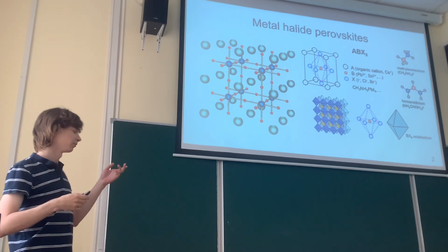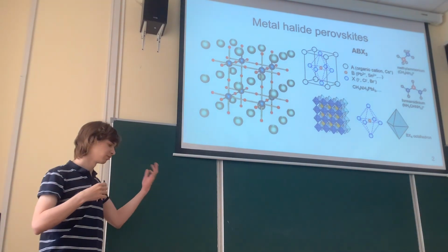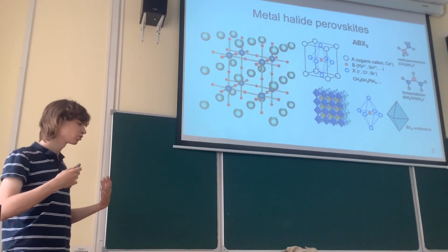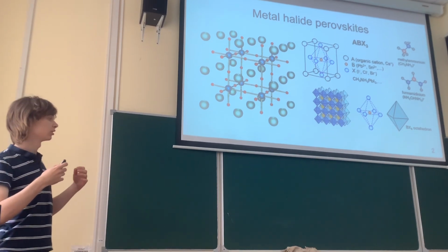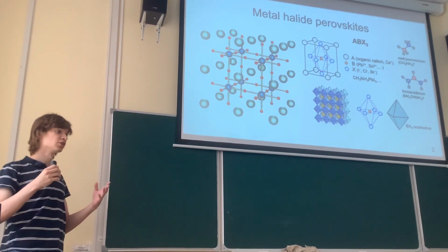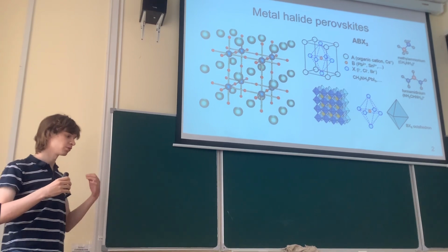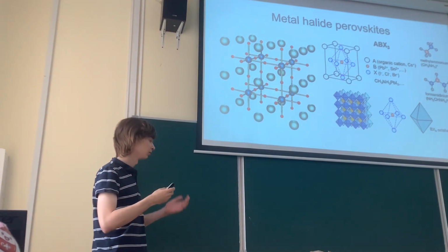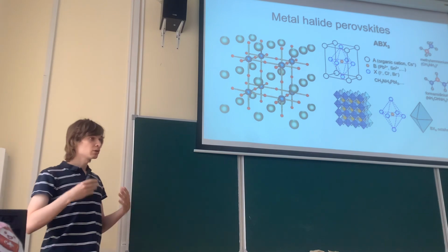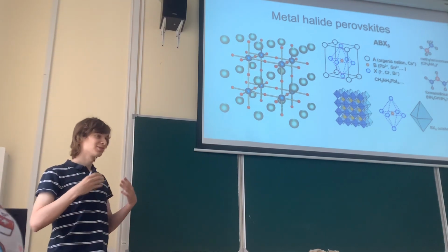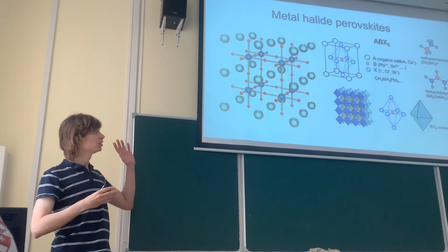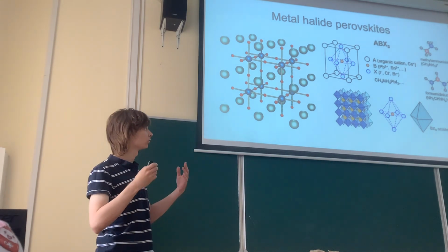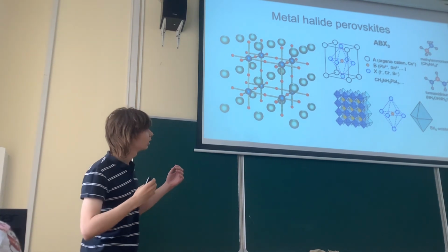They have charge carriers in them with very long lifetimes and so on. So nowadays the studies achieved a peak efficiency of about 24%, which is huge. It has already surpassed the devices that we used before. However, various calculations show that their peak efficiency can be higher, around 30%, which means that we still do not understand what recombination events happen there.